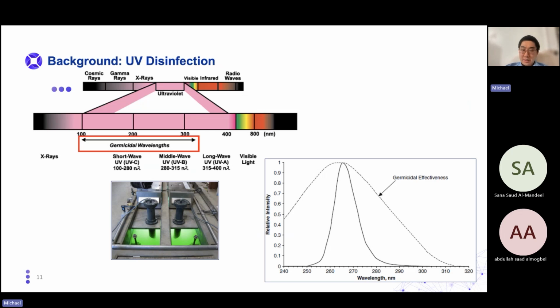I also should mention for UVLED for germicidal, the shorter wavelength you go, the harder it is, because the higher aluminum content of material you need, and the harder the material growth. So typically for germicidal UVLEDs, we target around 270 to 285 nanometers emission.